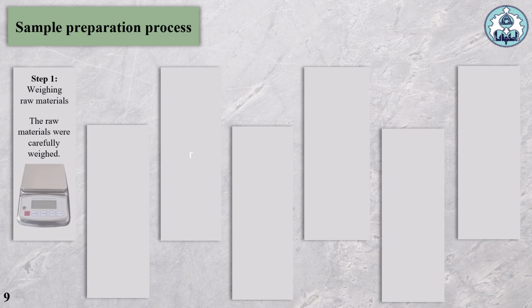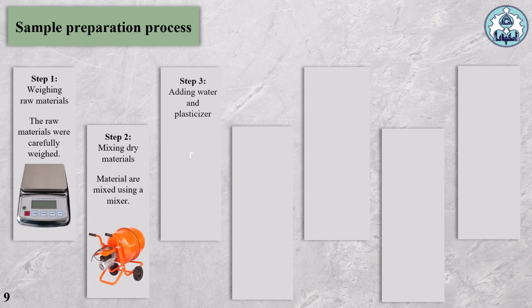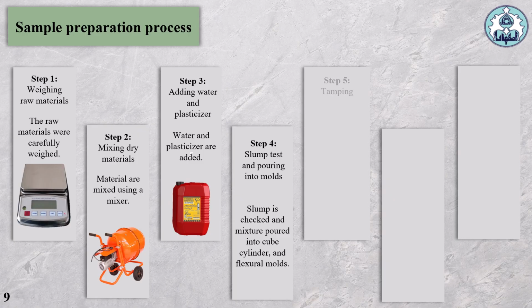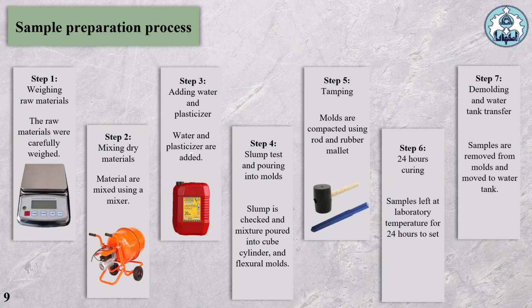The preparation process for all 3 concrete mixes followed 7 steps. First, all raw materials including cement, slag, aggregates, sand, water, and plasticizer were carefully weighed to ensure accurate proportions. Next, the dry materials were thoroughly mixed using a concrete mixer. Water and plasticizer were then added to the mixture, making it ready for casting.